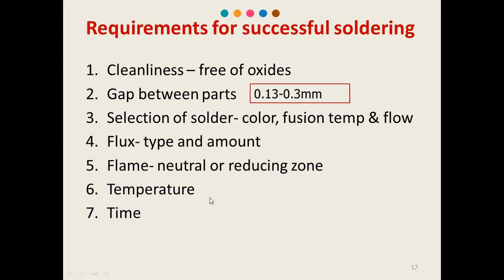Now the time. The flame should be kept in place until the filler metal has flowed completely into the connection, that is, until the flux has done its role of removal of the oxide layer, and then the solder metal has flowed into the gap. If the flame is applied for very little time, what will happen? There is incomplete filling of the joint with the parent metal, or flux inclusion occurs. And if a longer time is given, there is a possibility of diffusion. In both conditions, it will result in a weaker joint. So as soon as the solder metal has flowed, you should remove your flame.